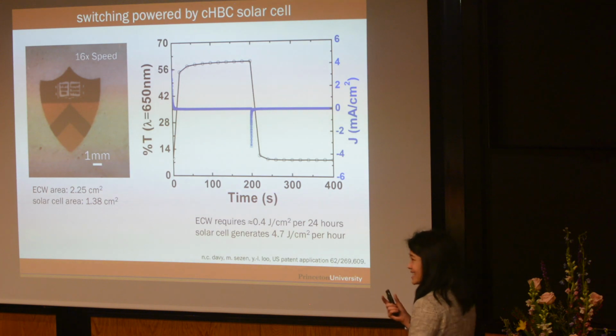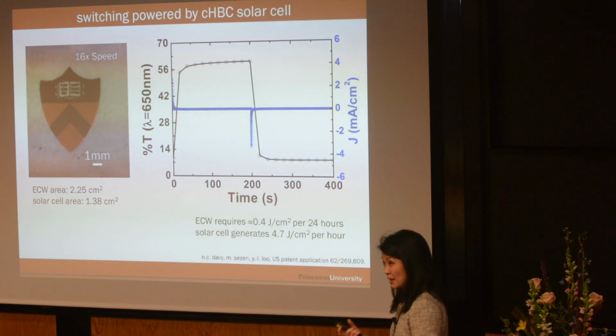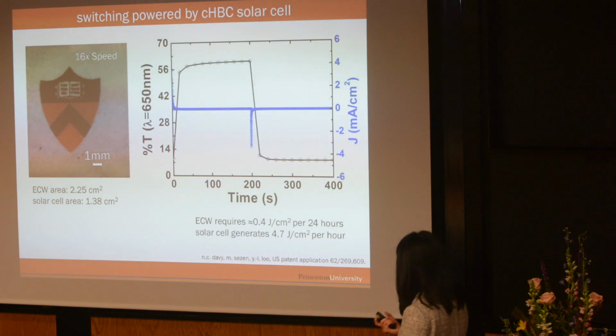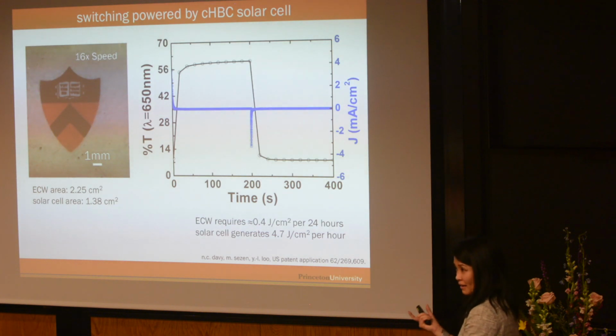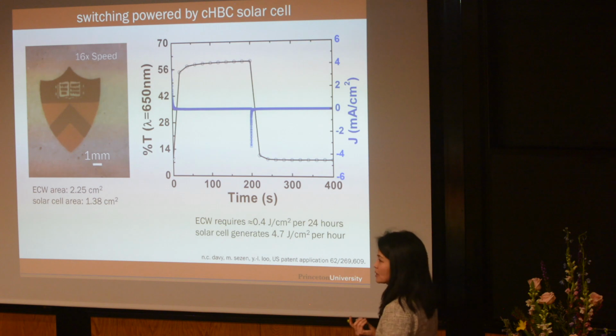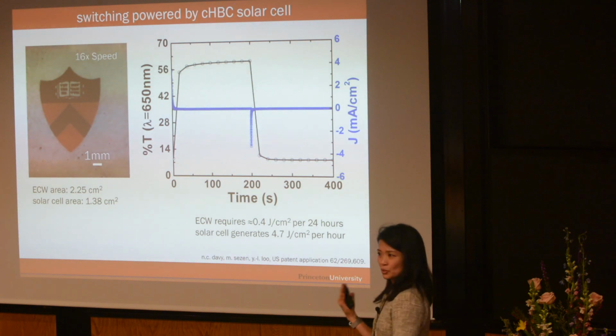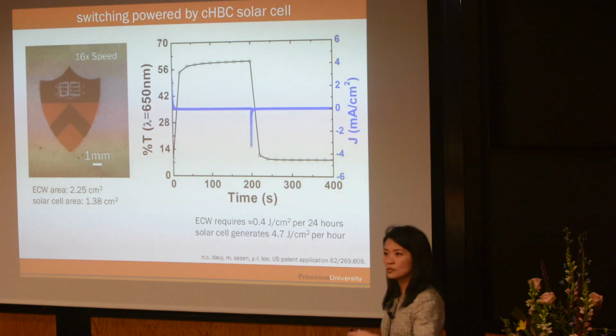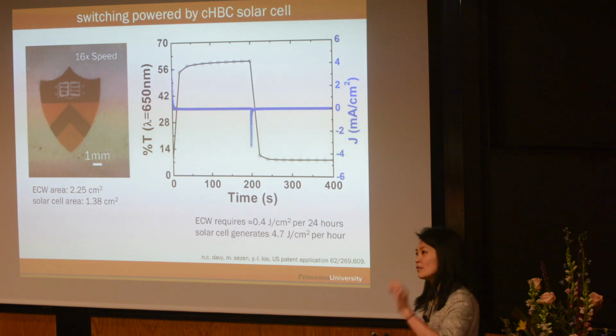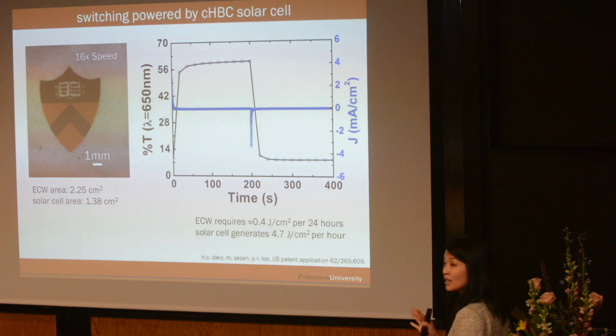So it turns out, like I said, electrochromic technology does not require a whole lot of power, but it does require power. With this polyaniline technology, you need about 0.4 joules per centimeter squared for 24 hours. That's including switching every hour plus this pulse every 15 minutes. Okay? Not a whole lot.